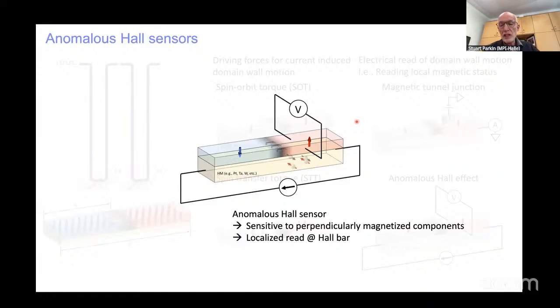Now, I mentioned before, we use optical means to detect the motion of domain walls. We basically apply current pulses, the domain walls move, we take a snapshot of the domain walls, we apply more current pulses, they move, we take another optical snapshot, and we look at the motion of the domain walls. An alternative technique is to use this anomalous Hall sensor device, as I mentioned earlier. And this is some very recent work we've done here, where we've used anomalous Hall sensors to explore the motion of domain walls in racetracks that are as narrow as 50 nanometers. So before, using optical Kerr techniques, the racetracks were 1 or 2 microns wide. Now we can look at racetracks only 50 nanometers wide, and we locally read the magnetization using a Hall sensor.